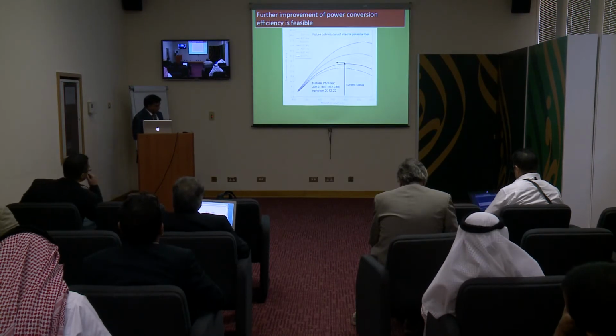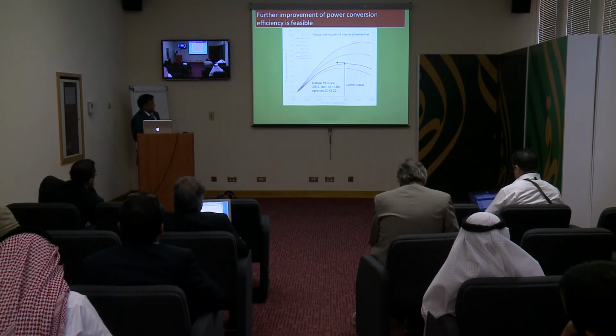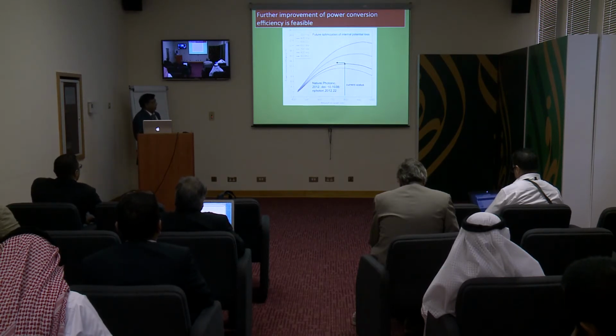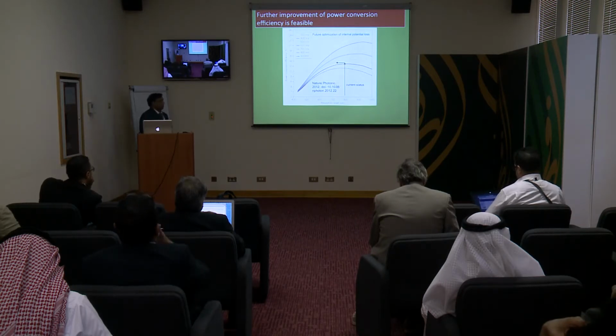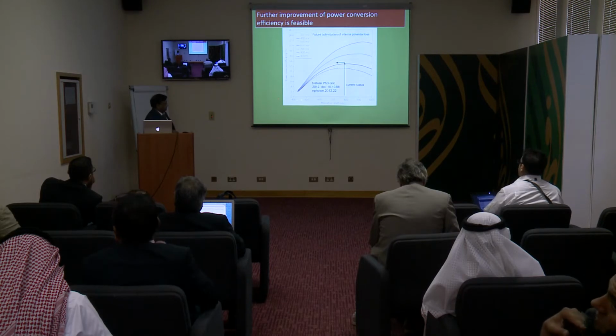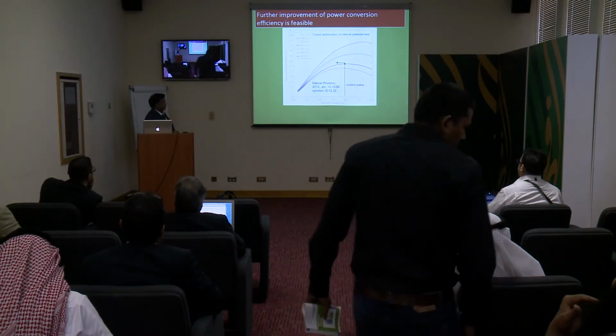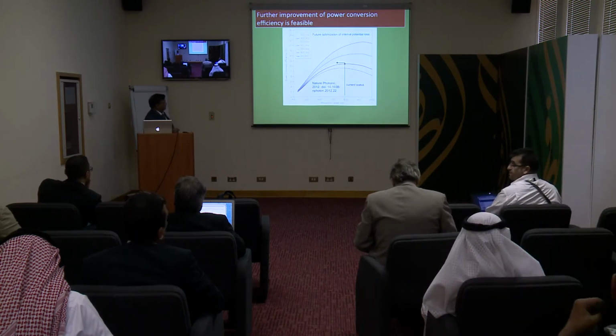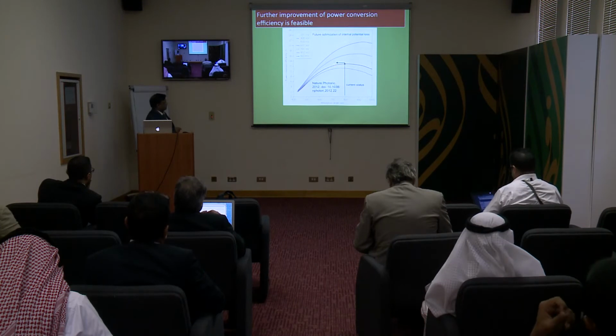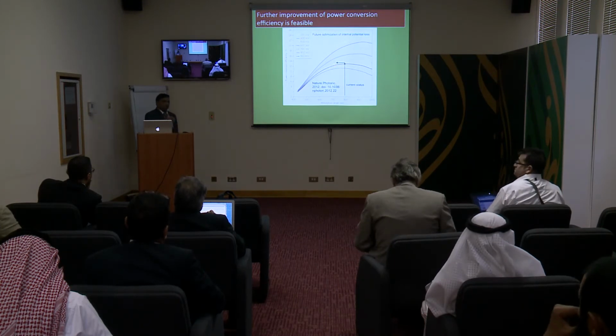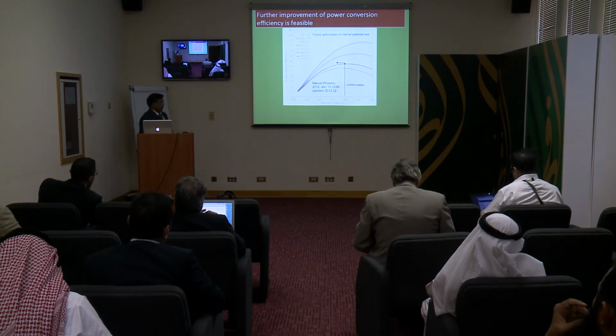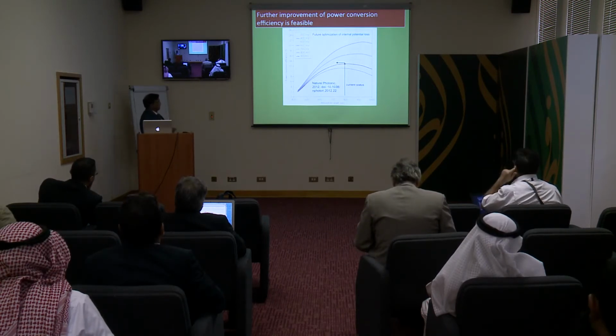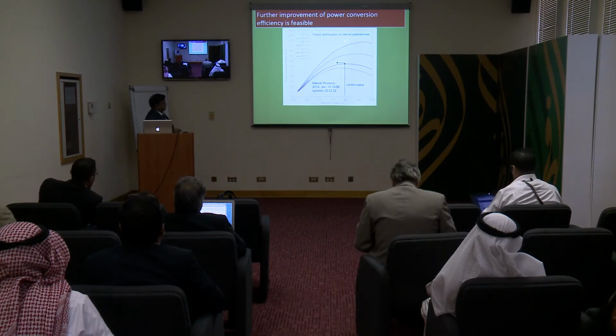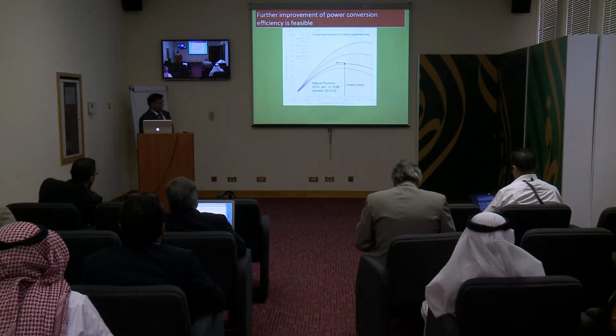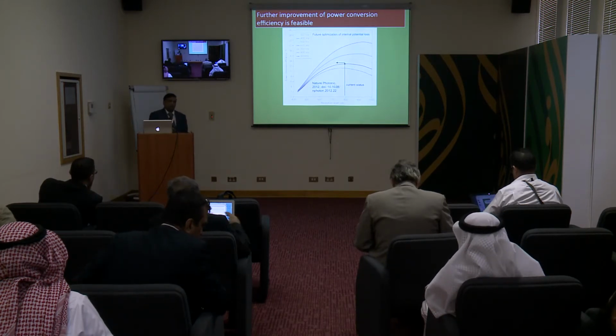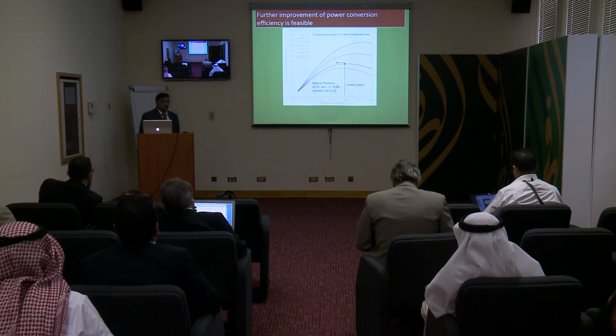For example, if you look at this figure, it is well prepared by taking into account that the injection efficiencies are 90%. The absorption spectrum is on the x-axis and the power conversion efficiency is here, plotted with different colors. This is the energy difference, the loss between the HOMO and the redox electrolyte. If the loss is 300 millivolts, which is the minimum one can see, you get a higher performance. Whereas if you take N3 and iodide redox electrolyte, the gap between these two is around 750 millivolts.